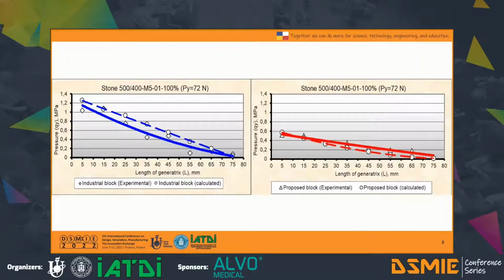The result of experiments using an industrial block shows that the change in the contact pressure along the length of the stone is within 1.04 to 0.07 megapascals. The proposed construction of the block made it possible to reduce the change in contact pressure along the length of the stone.